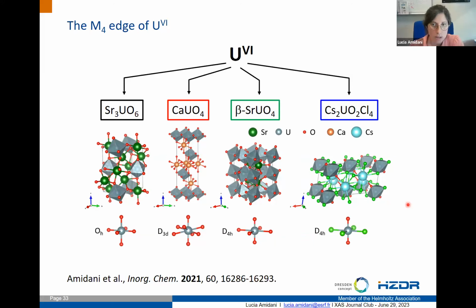So let's go to the case. We had four solid samples that all contain uranium-6+, where uranium has a local coordination that goes from 6 oxygens in an almost perfect octahedral configuration towards the prototypical case of uranium-6, which is uranyl, where we have 2 very short bonds with oxygen and some equatorial ligands that can be 4, 5, or 6, but here we have 4. So basically we go from OH to D4H, with some intermediate cases.